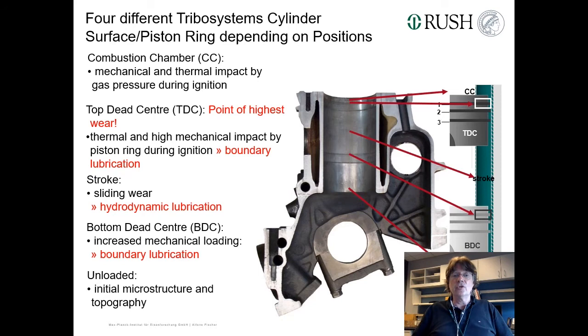So first thing is, we got a cylinder that had been for 60,000 kilometers on the German Autobahn, in order to find out what is going on in reality. This is, you know, macro, with a path to the stadium. And we found it's not one tribological system. It's four tribological systems in our case. It's the combustion chamber, the top dead center, the stroke, the bottom dead center, and we can compare whatever happened here has started with something down here in the unloaded region. And so we were able to compare over the entire cylinder wall, as well as on the ring side.